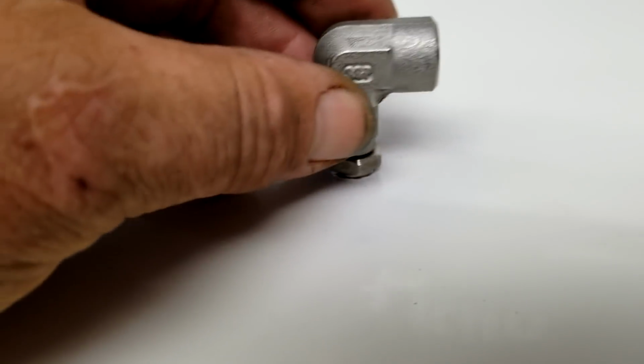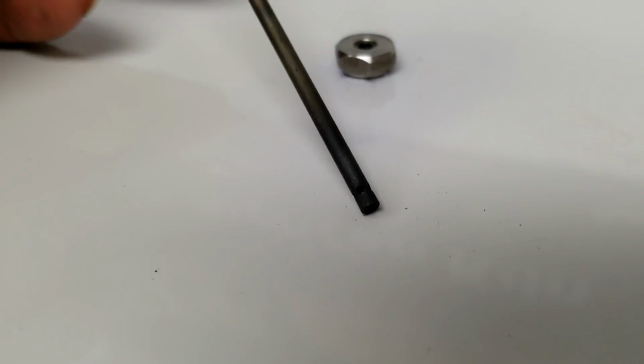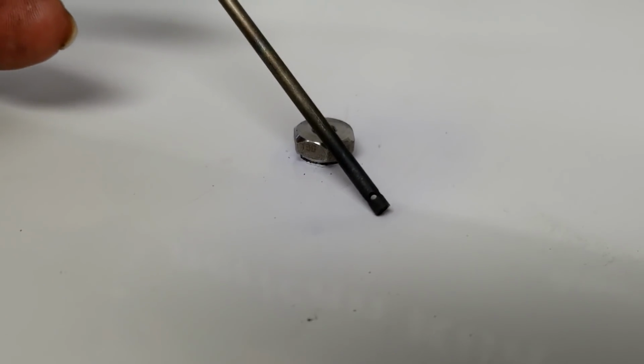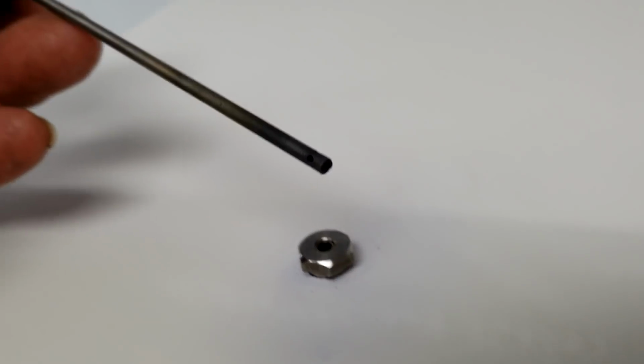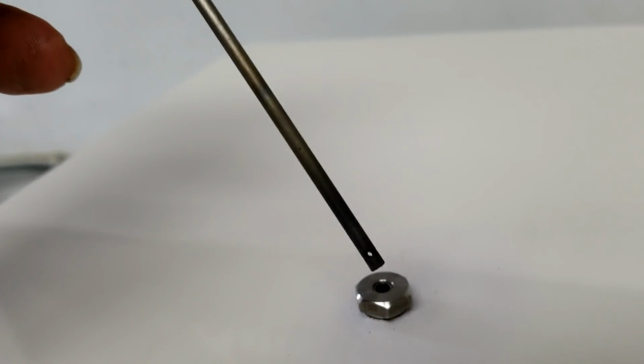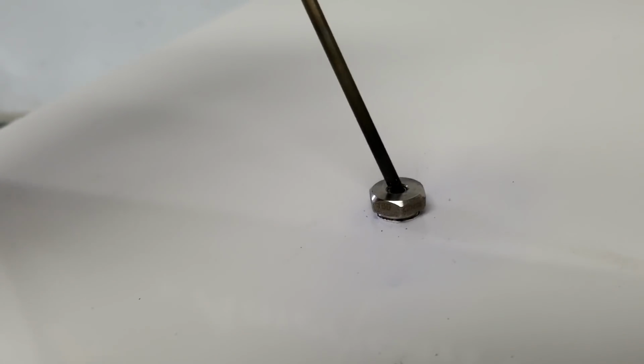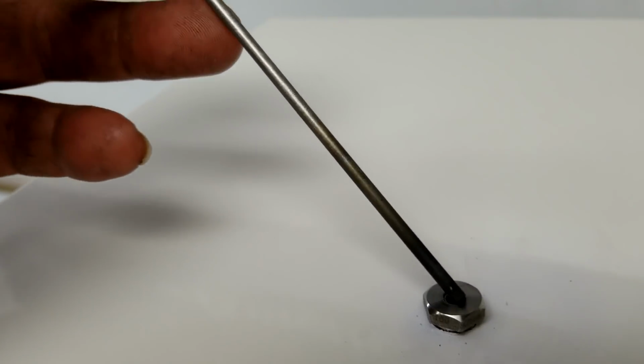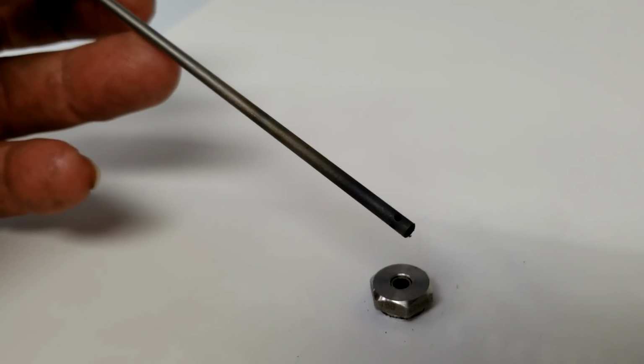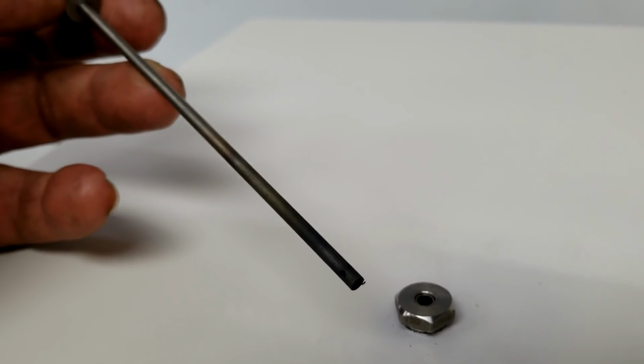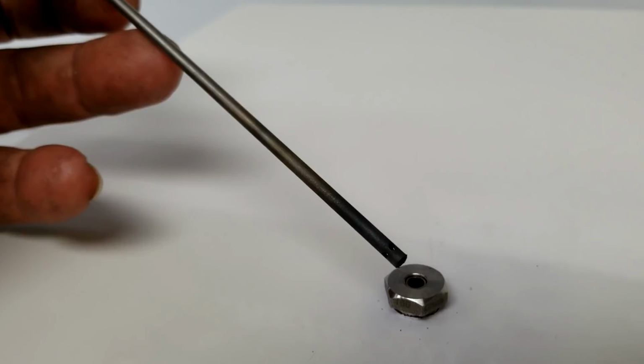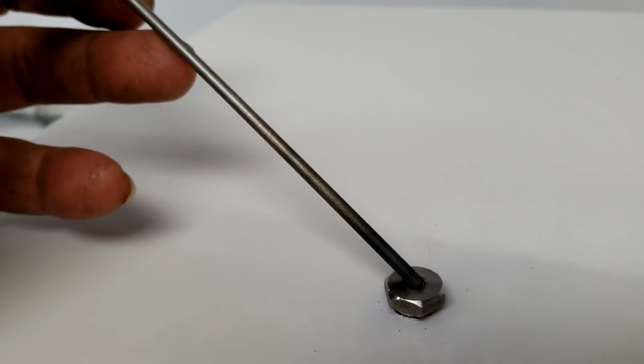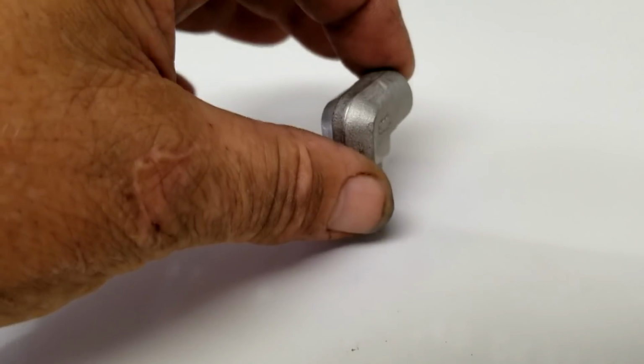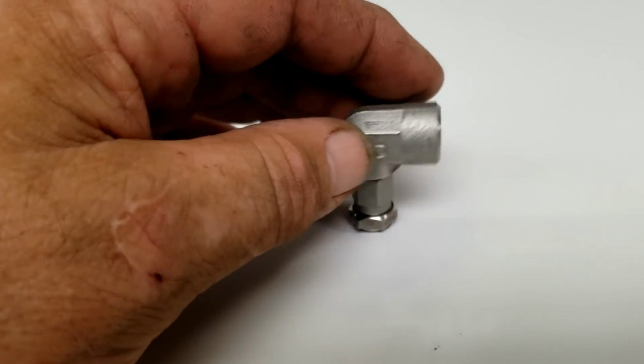All right, and it's the same tip of the injector that we had before. Four cross-drilled holes, plugged at the end, Inconel. And I did this test with no argon flowing. So you can leave this injector in all the time. There was no damage there. I mean, the Inconel's discolored and turned black, but it didn't scale up and didn't make it where I couldn't get it out of the sleeve anymore. And you could give it a quick polish with Scotch-Brite if you wanted to after the oven's cool.